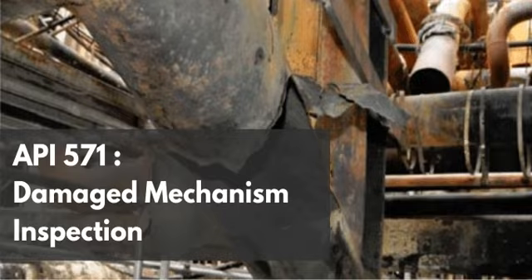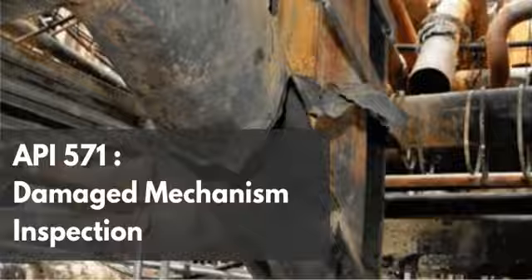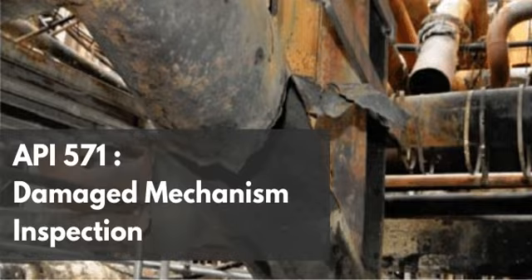Exactly. Shear wave is designed to find planar defects. When it hits a broad area of uniform thinning, the signal scatters and you realize you have thinning. But because this amine corrosion creates such a sharp, localized canyon right at the weld root, the sound wave strikes the steep wall of that canyon and returns a massive, sharp echo. Wow. The technology is working perfectly, but the physical geometry of the corrosion is actively deceiving the interpretation of the data. So what does this all mean?